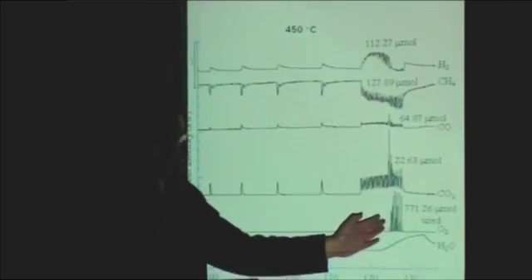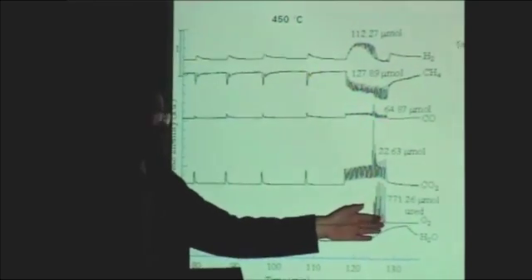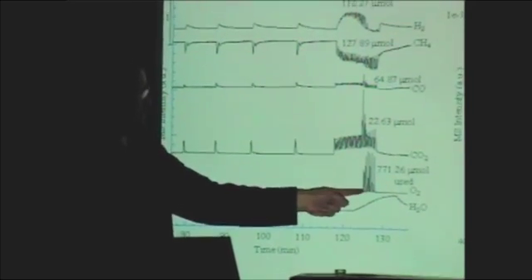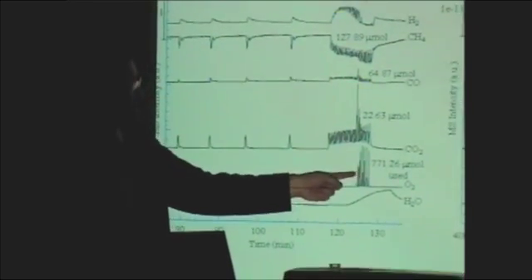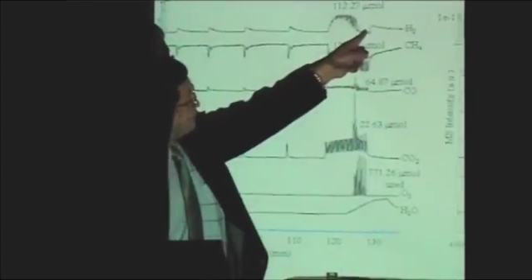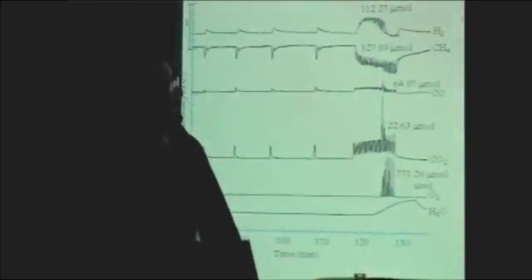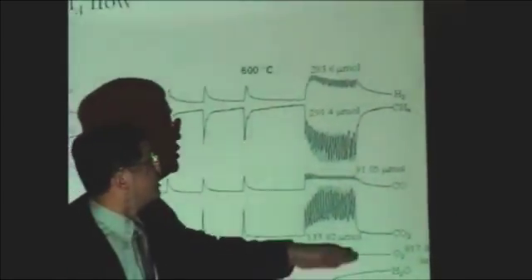And later on we start to break through. When oxygen breaks through, that means there's a lot of extra oxygen coming out from the oven or the reactor here, and there's a lot of extra oxygen in the reactor. As a result, that oxygen is reacting hydrogen away here. And at higher temperature, we see more water formation.